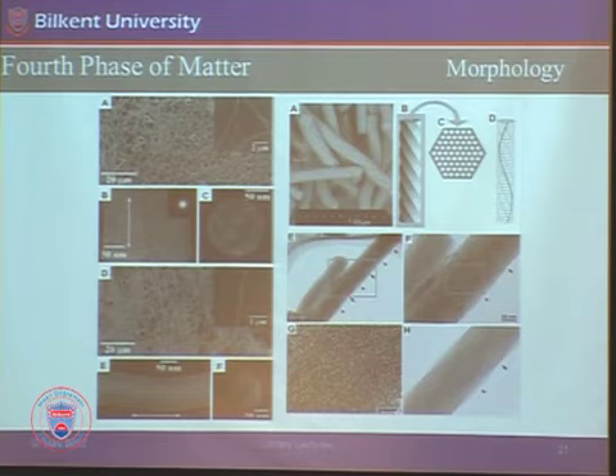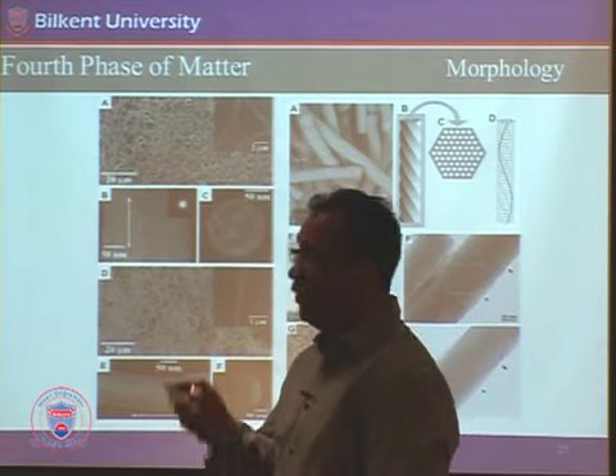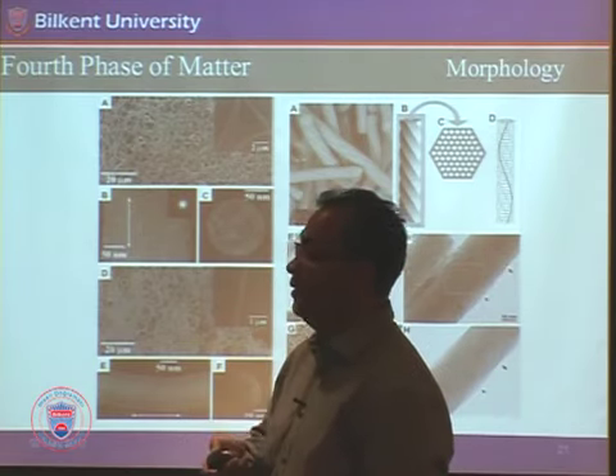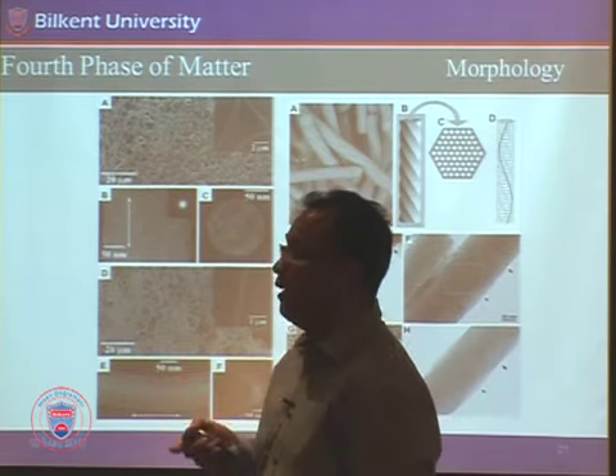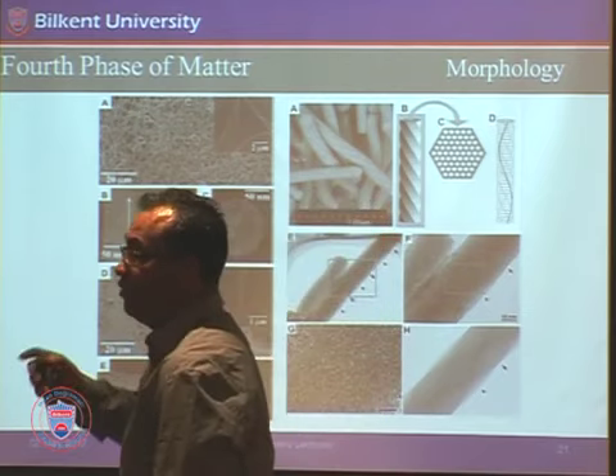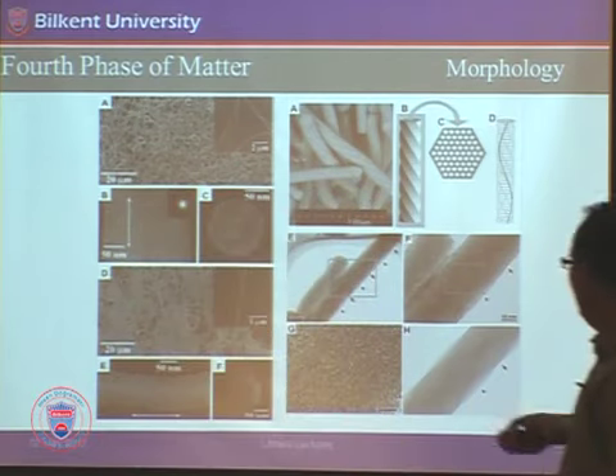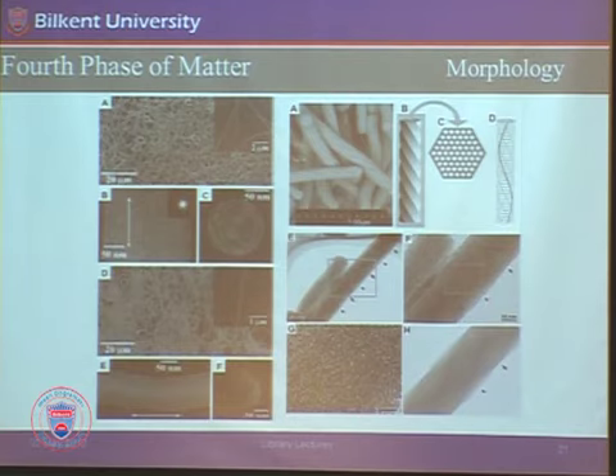But these molecules can assemble these structures, and these structures are resistive to heat. When you burn the organic out, you end up with tunnels in these. And these days, people are using these for modifying the surface for catalysis, for example, or to put drugs inside. They can put the drugs in and let the drug come out very slowly, a slow-release drug application. Many applications anyway. And this is the picture basically.